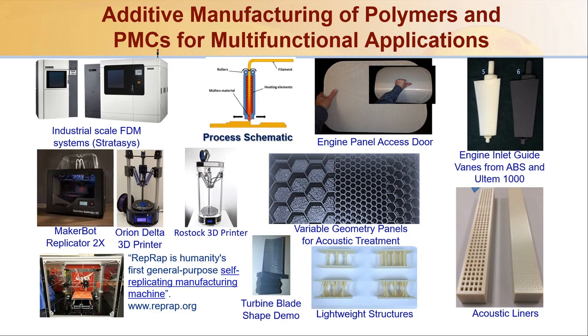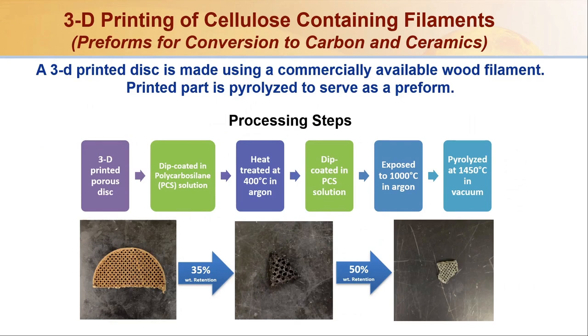It's a pretty exciting area to talk about, but in the rest of the time I will not get too much into this particular field. Another area where we did a lot of work is on 3D printing of cellulose-containing filaments, where you can print wood-containing or cellulose-containing preforms and convert them to carbon and ceramics. Typically in this case, you have the wood filaments, so you just 3D print a porous disc or dense part. We dip coated that in polycarbosilane solution, then heat treated it at 400 degrees C in argon, dip coated again in PCS solution, exposed it to 1000 degrees C in argon, and then pyrolyzed at 1450 degrees C.